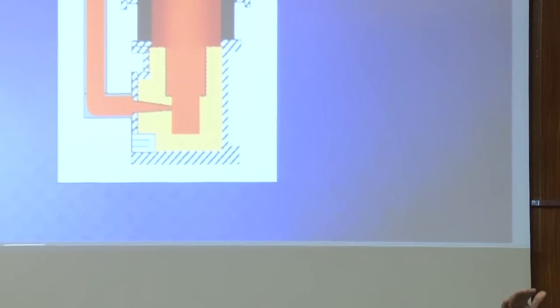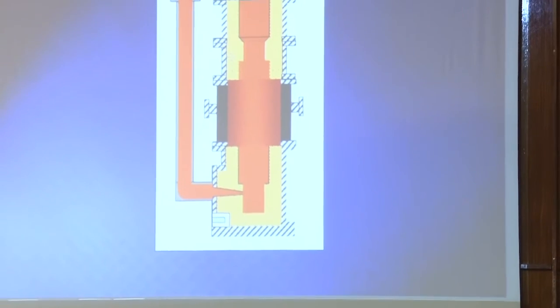Then, very quickly, I will give you how we cast. This also should have been in animation, but I can describe it. We cast the roll vertically like that. You need the surface barrel with a high abrasion resistance. That means high hardness, and next you need high fracture toughness with lower hardness, and that's why we cast the main body of the roll, the roll barrel, in cast iron chill.